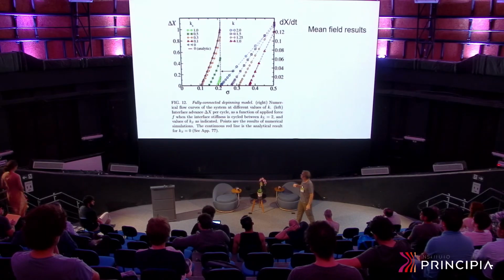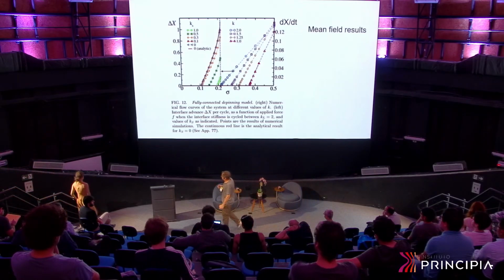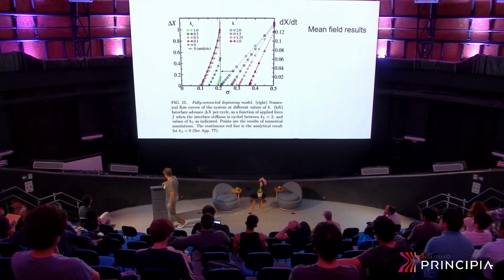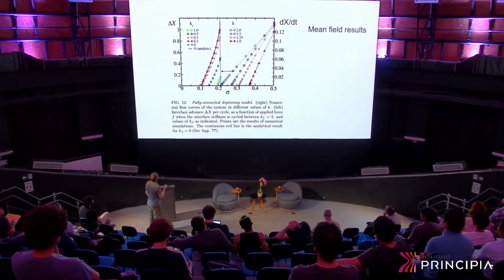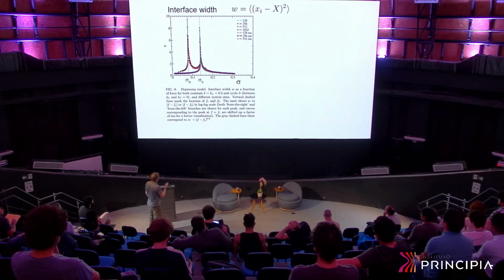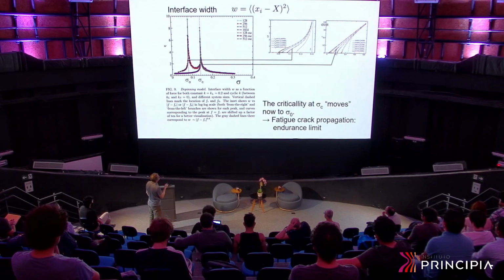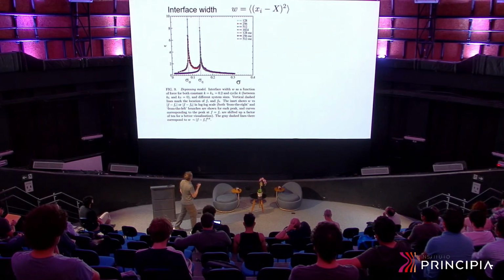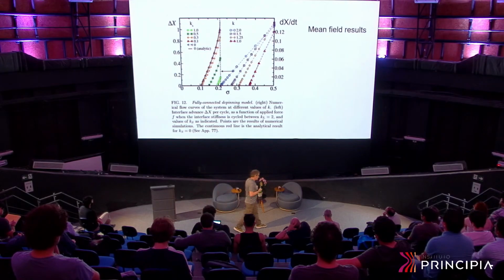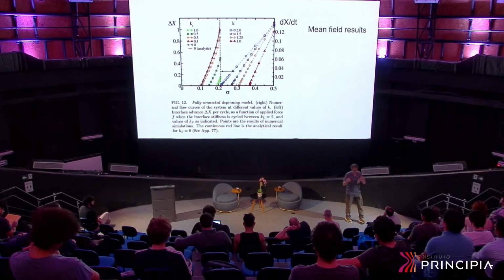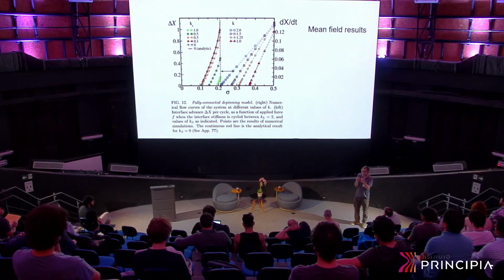And in fatigue crack propagation, there is an interesting phenomenon that is called the endurance limit of fatigue crack propagation. There are materials for which, if you apply a cycle of increase and decrease of stress that is lower than some critical value, the crack does not increase anymore.